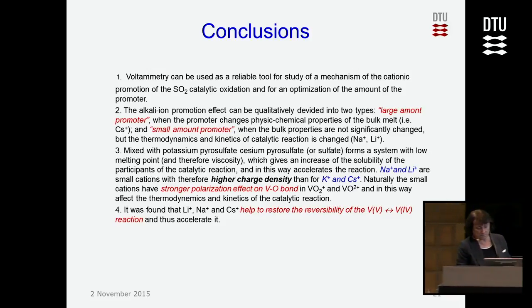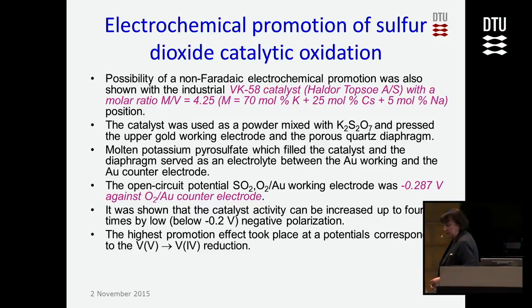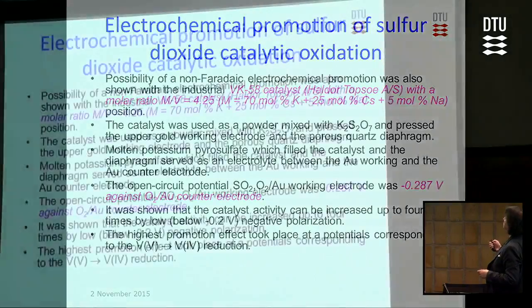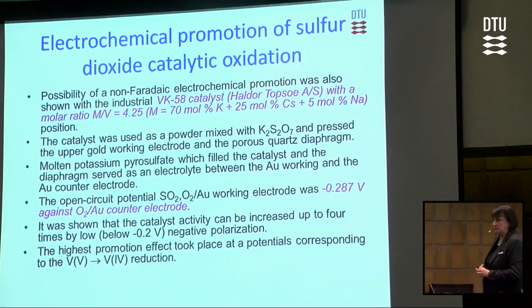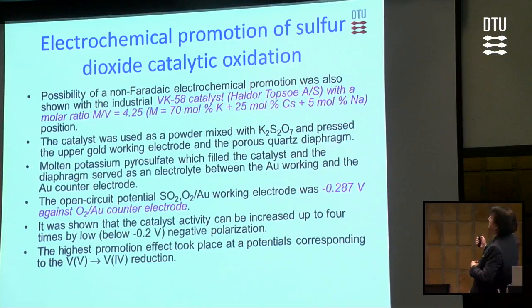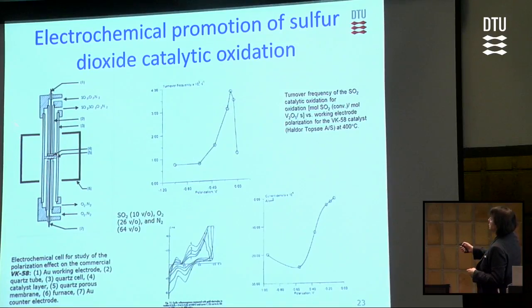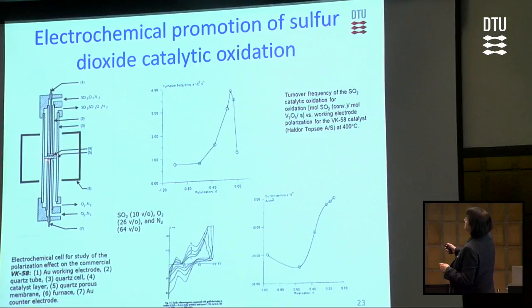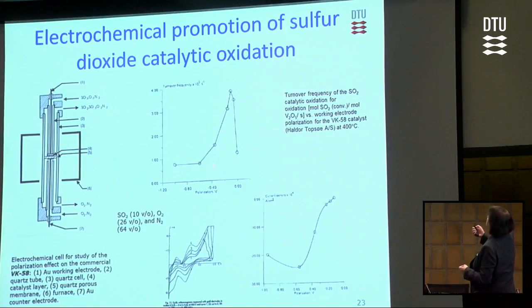Okay. For the first time, we actually did try to study electrochemical promotion using a Topsoe catalyst. Commercial, like this. I don't know if you still produce them or not. You don't. Okay, so 5 mol% of sodium. So what we did, we used this cell. This was a porous Pyrex. Then we have 2 gold electrodes in the form of mesh. And between this electrode and this porous membrane, we milled this catalyst, and then we put the catalyst particles here. We filled this porous membrane with molten electrolyte, and we got promotion.